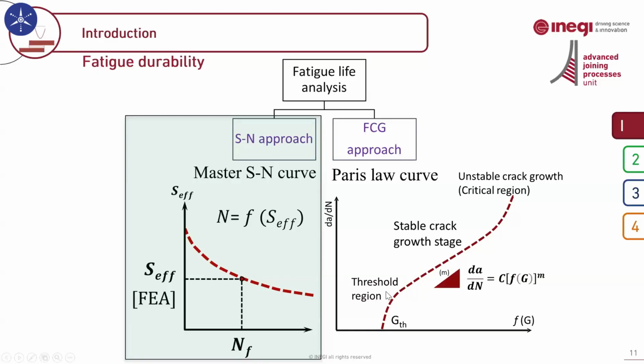Here we have a Paris law curve. Again, similar to the SN approach, here we should develop and construct a master Paris law curve. So to obtain the master Paris law curve, it's really important to select an appropriate Paris law parameter. Similar to the SN methodology, the challenge here is to understand what the suitable and appropriate Paris law parameter is. In case we select a correct one, then we will be able to collapse all the Paris law curves obtained for different loading and environmental conditions into a single curve, which we call the master Paris law curve.